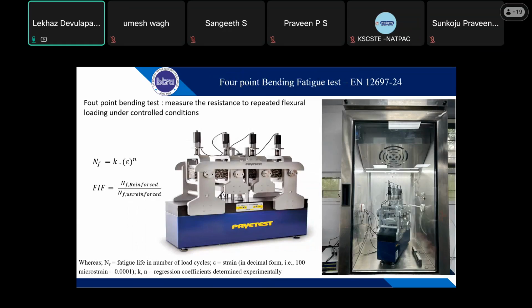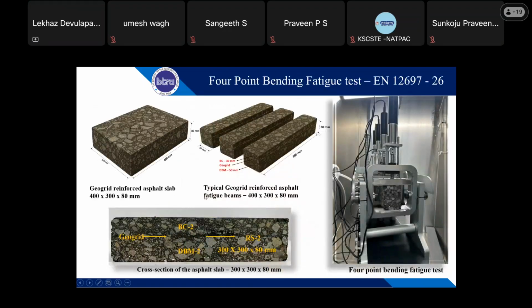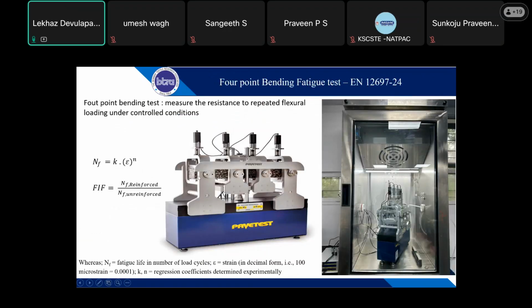Then we needed to check how the geogrids perform towards fatigue or crack resistance. For that we need to do a 4-point bending test. This is the 4-point bending fatigue test which we conducted as per the EN 12697-24 specification. Here we prepare a slab and a beam, which is placed between 4 supports, and the load is applied at the center between the 2 supports, so it is in a pure bending moment without any shear.